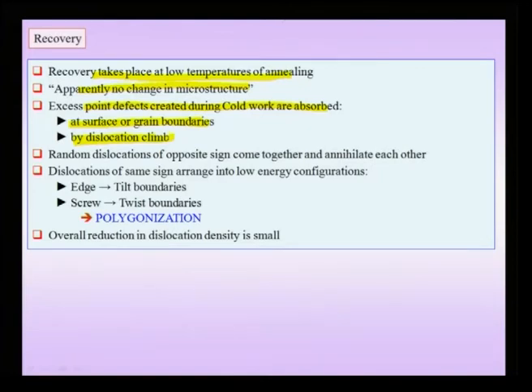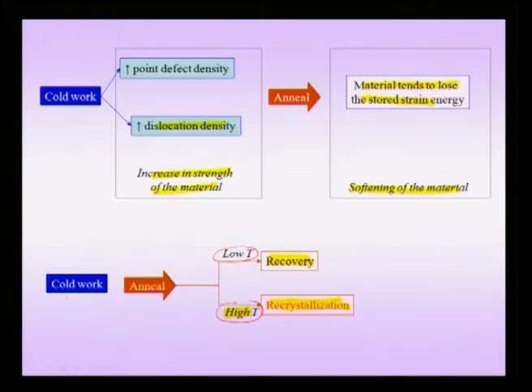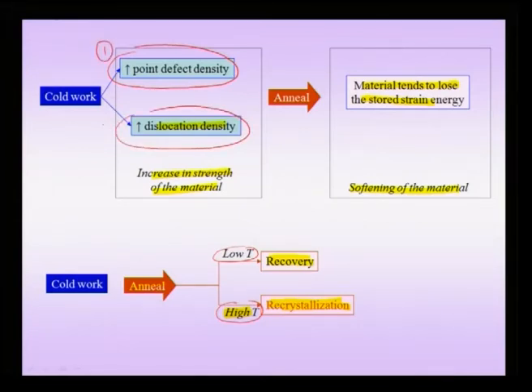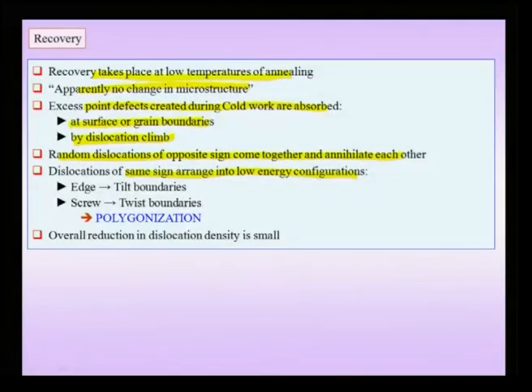Now, additionally, one more thing happens to dislocations: random dislocations of opposite sign come together and annihilate each other. We will see a schematic of that in the next slide, and the dislocations of the same sign tend to arrange into a low energy configuration. First thing, of course, you have two kinds of defects which we discussed before when we talked about cold work. One is point defects, and typically the important one being vacancies, and the second one is dislocations. So, we have two kinds of defects which are important, which have been altered during cold work, and when you are doing recovery, both these defects are affected, more so the vacancies and less the dislocations.